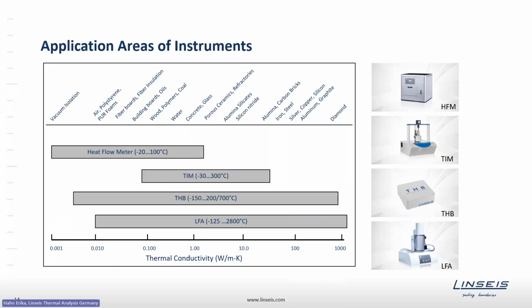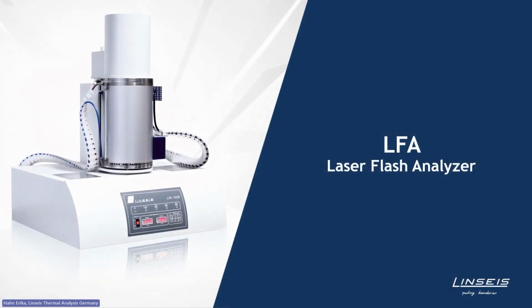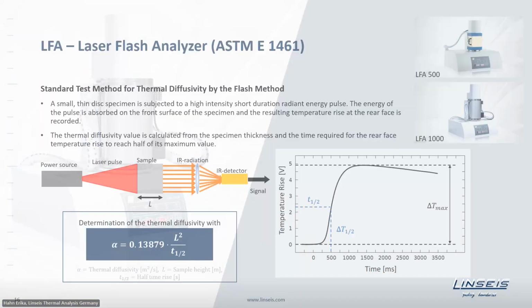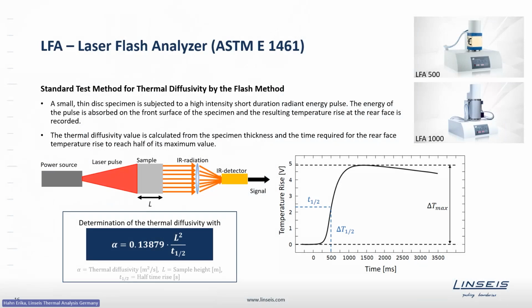So now we start with having a look at the instruments a little bit more closely, at the measurement methods, and we start here with the laser flash analyzer. The laser flash measurement is the standardized measurement principle according to ASTM E1461, and it is described where a small, thin disk specimen is subjected to a high-intensity, short-duration radiant energy pulse, and the energy of the pulse is then absorbed on the front surface of the specimen, and the resulting temperature rise at the rear face is recorded. This is illustrated here. So we have the power source, the sample, and the infrared detector as the main parts.